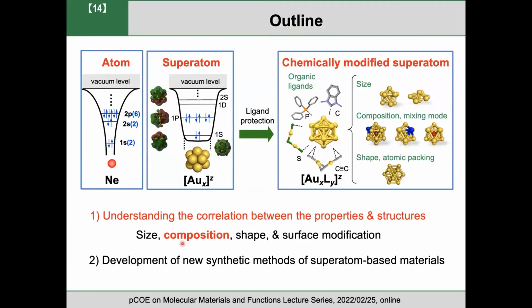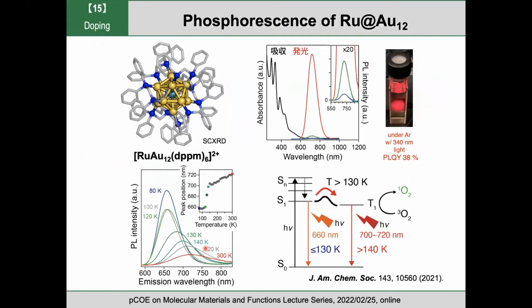Okay, let me move on to the effect of composition on the properties. I focus on the photoluminescence properties. Recently we successfully doped a single ruthenium atom at the center of the gold-12 core. And this is a single crystal structure. These clusters exhibit intense photoluminescence with a quantum yield of 38% in the absence of oxygen. But when we introduce oxygen, this luminescence is quenched almost completely. And we also observe the formation of singlet oxygen under photoirradiation. So we assign this band as phosphorescence from the triplet state of the gold clusters.